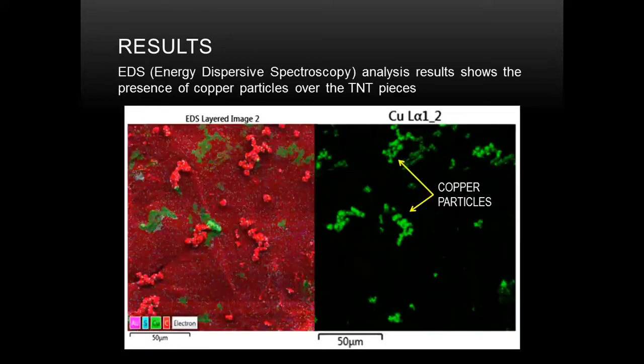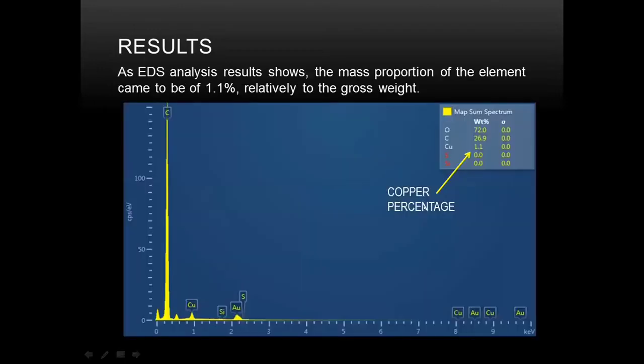The analysis shows the presence of copper particles over the TNT piece, as you can see here in these posted images. And here you can see that it is indeed copper. The results show the mass proportion of the element is around 1% relative to the gross weight. And you can see here other elements, such as carbon and oxygen, to be around 27 and 72%, and around 1% of copper, which we will discuss for safety reasons later.